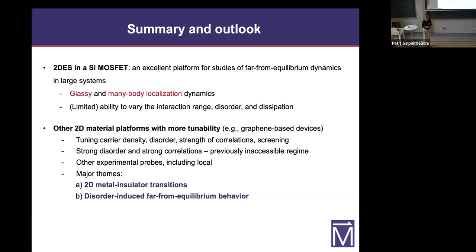I think in glasses you have a kind of effective temperature, fluctuation, dissipation. This is true, but only when you're not very far from equilibrium. If you're far, it doesn't work. More was like, can we use it as a probe of thermalization, that the actual fluctuation dissipation relation? Oh yeah, I think, well, yeah. But as Anu said, in the glassy case, when you're not too far, it works with some effective temperature. So this was done by Leticia Cugliandolo and Jorge Kurchan at Sorbonne.